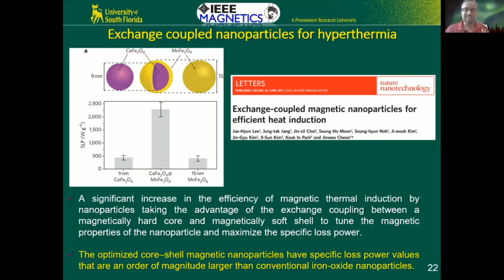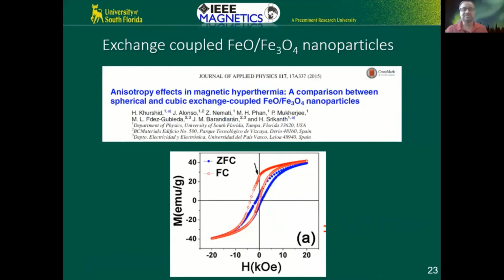And so I gave this as a challenge to one of my postdocs, and she came back with this. She did it. She made exchange-coupled core shell iron oxide, 2 different phases of iron oxide. FeO is the Wüstite phase. It's actually a lesser known phase of iron oxide, and it's antiferromagnetic. Now that's our core. And remember, our outside has to be biocompatible, right?